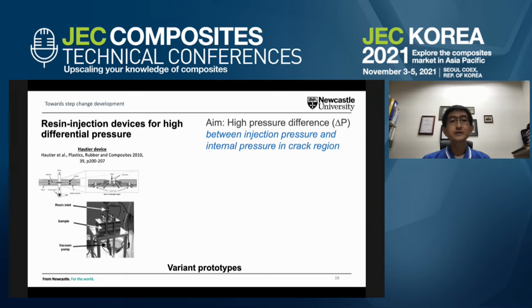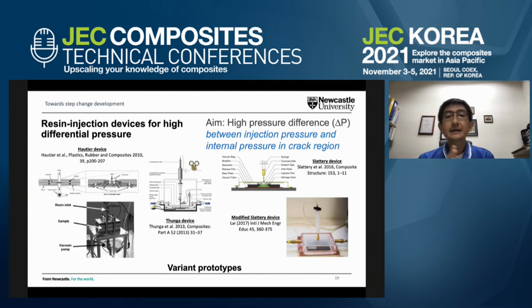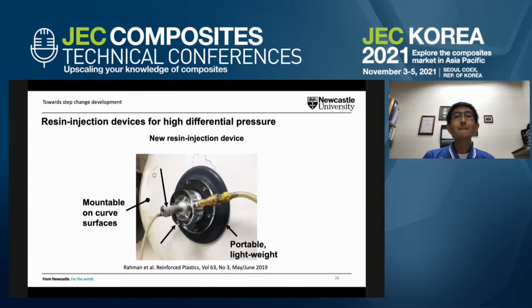We find that this approach has been also adopted in earlier studies since 2010 and until quite recently. But we find that most of these prototypes that are reported in the literature are relatively not very straightforward to operate, and also bulky, and therefore not portable, particularly if you want to really think about bringing it into the field for repair. So what we did was, after several iterations of design and looking at seeing if we can improve on the existing repair system, we finally came out with what we have here as shown, a portable, lightweight device that also can be mounted not just on flat surfaces, but also on curved surfaces. And it also has vacuum ports to control the pressure to achieve high differential pressure.